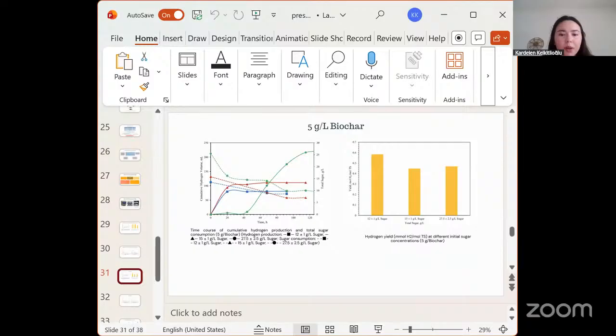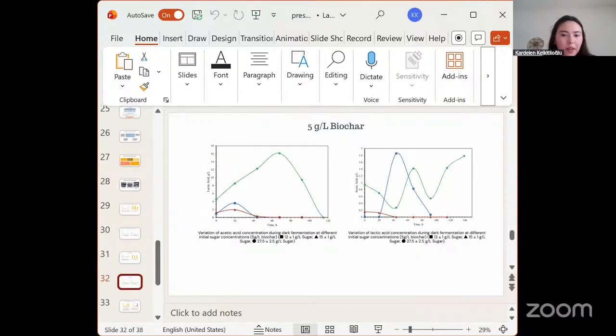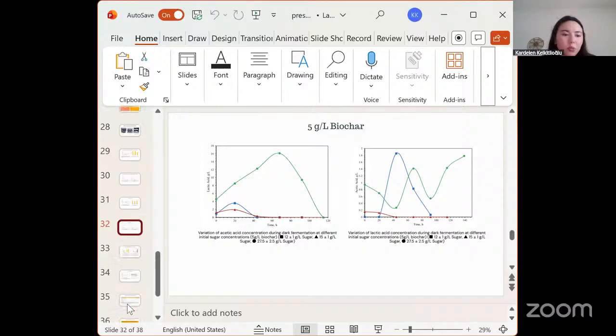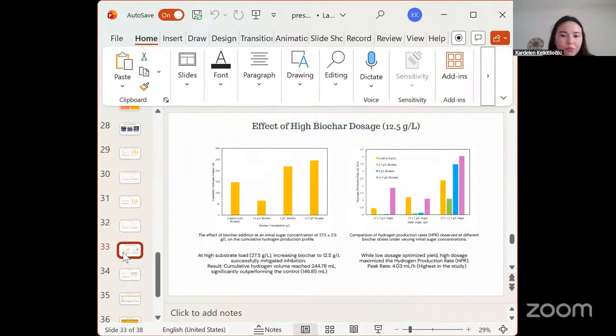At 5 grams per liter biochar, the system clearly recovers. Hydrogen production is now sustained even at high sugar loading, with consistent yields across all concentrations. These acid profiles confirm the mechanism. Lactic acid is produced but then depleted, evidence of biochar adsorption. At 12.5 grams per liter of biochar, inhibition at high sugar loading was successfully mitigated. Cumulative hydrogen reached 244 milliliters.